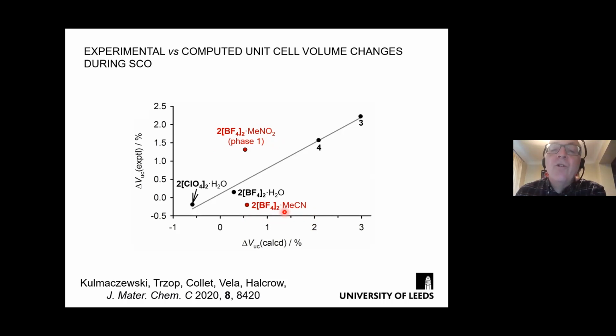However, this one is also not reproduced. The calculated crystal structure for this compound has a unit cell volume which is too high. It should have a negative unit cell volume change, but that's not calculated by the DFT. Now, it's not the negative volume change that's the problem. This compound also has a negative volume change, but this compound is calculated correctly. It's only this one which is not. So I think this is telling us something.